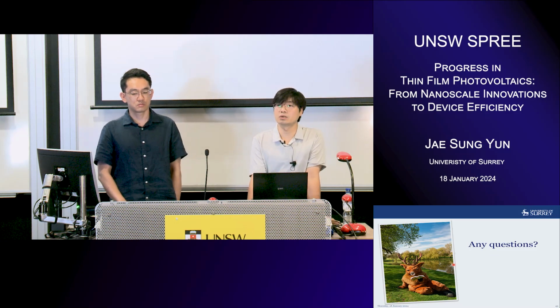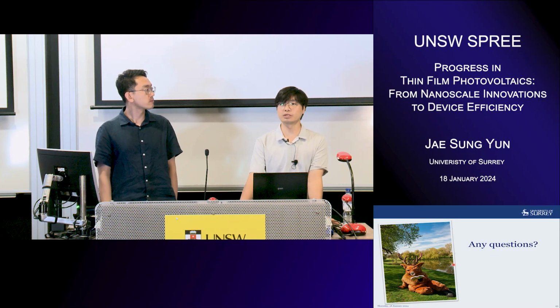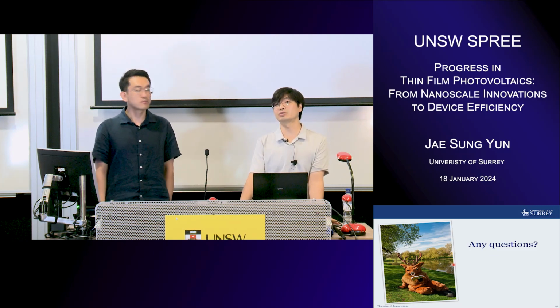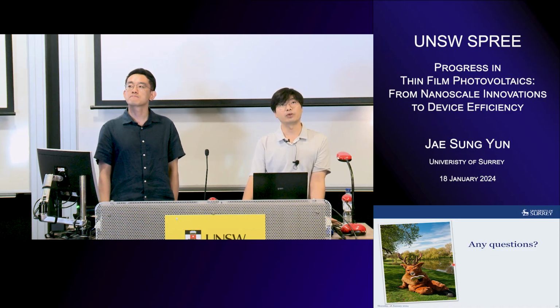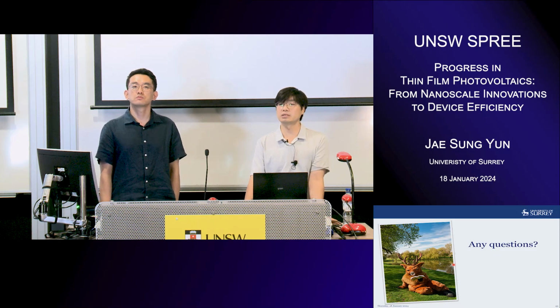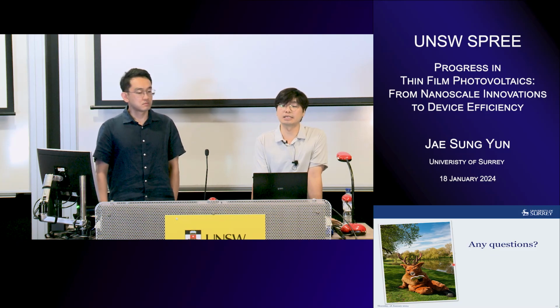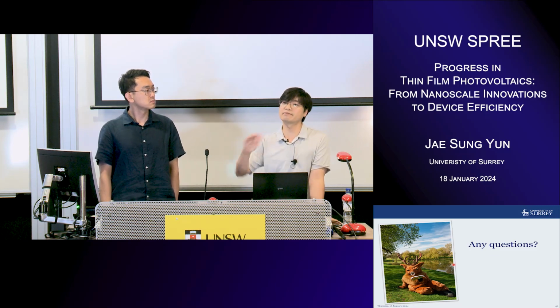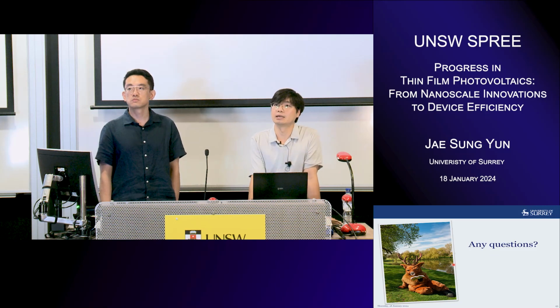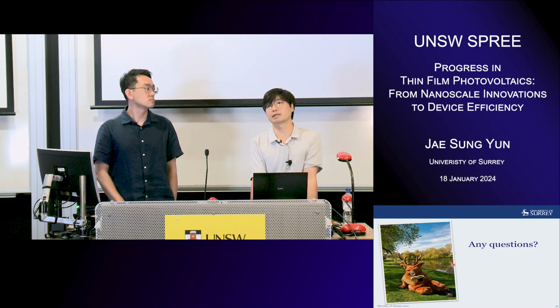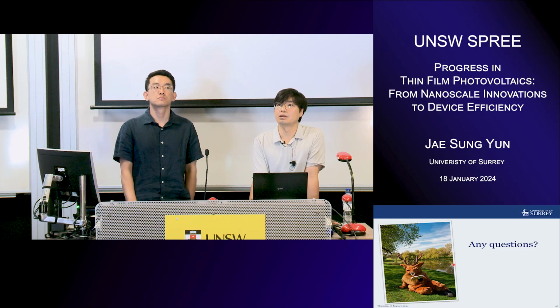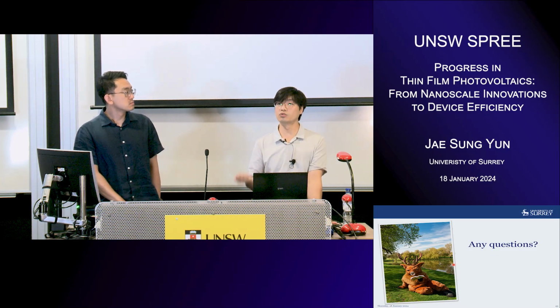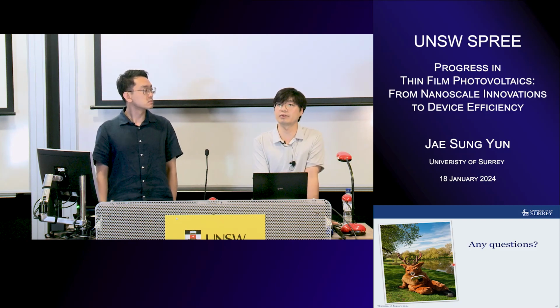I think ideally having 0% bromide would be good, but we can't enlarge the band gap. So eventually we will need to have bromide in some sense. But if we don't have bromide, I believe there isn't going to be much phase segregation. So for 5%, from my results, there isn't much phase segregation, and it's enough in terms of phase segregation and stability. Have we checked the characterization at 85 degrees? No, we haven't checked that one. We only checked the wide band gap perovskites at room temperature. Do we have the capability of checking that at 85 degrees? Yes, we can. We can even try high temperature using KPFM to check the phase segregation.